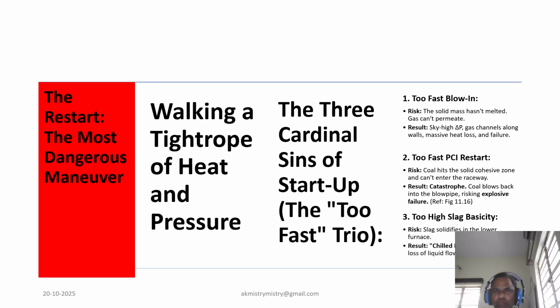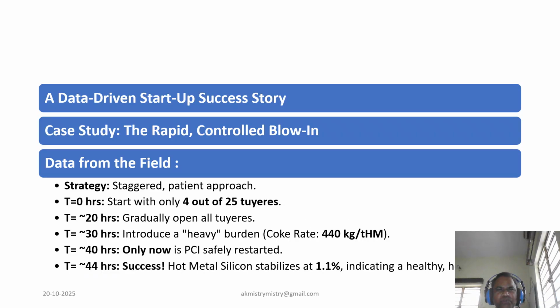So, what does a successful restart look like? Let's look at a data-driven success story. A rapid but, more importantly, controlled blow-in. The strategy was all about a staggered, partial approach. At time zero, they started with only 4 out of 25 tuyeres, just a whisper of air. After about 20 hours, they gradually opened all the tuyeres. At about 30 hours, they introduced a heavy burden with a coke rate of 440 kilograms per ton of iron